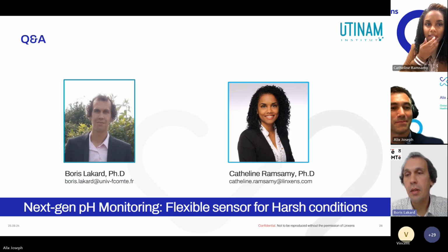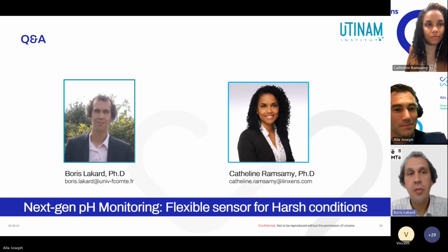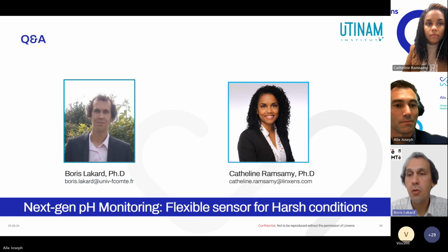I think it's better to do a calibration before, to have the real slope of the evolution of the potential as a function of pH. From my point of view, but it can be a calibration with two solutions only. It's not necessary to use many solutions to have a very accurate calibration. You can do as you do when you have a pH meter. You can take 2 or 3 solutions and you can do the calibration.